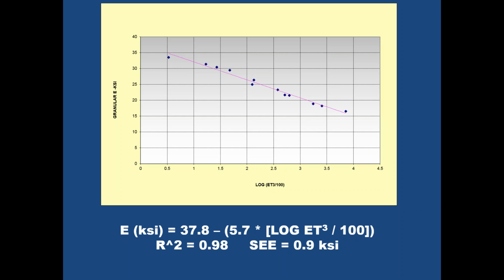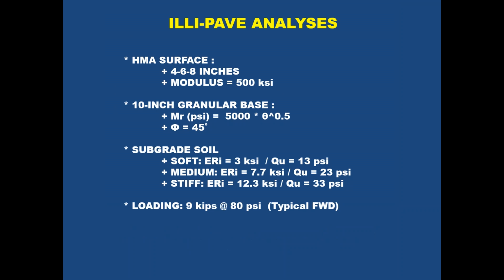So, you know, we need to factor in the fact that if we have thick surfaces and high modulus surfaces, the modulus developed in granular materials will be quite low. We ran some ILLI-PAVE analyses to demonstrate this effect, kept the modulus consistent at 500 KSI, 4, 6, and 8 inches of hot mix, a 10-inch granular base. Notice it's 5,000 theta to the 0.5. That's a ballpark, reasonable input for a crushed stone. The friction angle, 45 degrees.